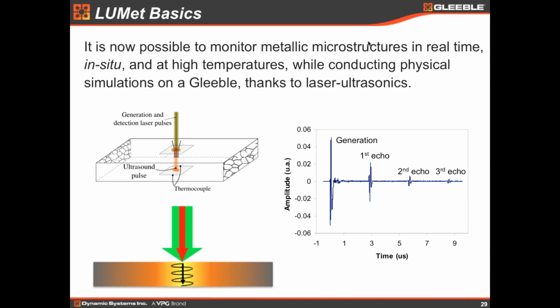The other thing that we often get from the Lumet is the grain size. The grain size can be related directly to what we call the decay envelope, or the reduction of energy of each echo. The amount of energy that's scattered as that echo moves through the sample and back to the surface is directly related to the grain size. So we can make a correlation curve and understand what the grain size is based on the decay envelope of that echo.